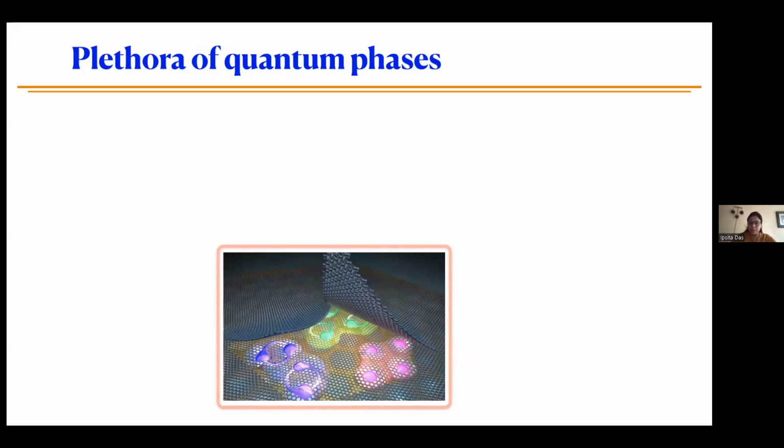This theory was out there from 2011 and people were trying to make these devices, but the 1.1 degree rotation between the two graphene sheets is not a stable configuration. Most of the time when we try to make these devices, they relax back to a more stable configuration away from 1.1 degrees, and we end up not having properly twisted devices.